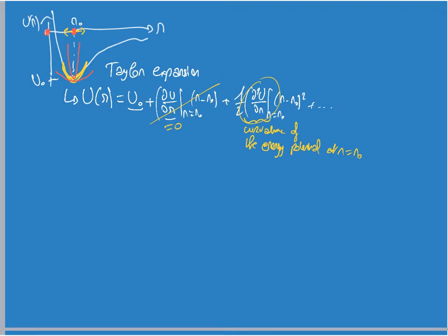So what we can do is realize that this looks very similar to the energy of a spring. If you have 2 points that are separated away from each other and attached with a given spring with a spring constant K, then the energy is given by 1/2 times the spring constant K times the elongation squared, the elongation being the distance L between the 2 points minus the equilibrium distance L naught, when the spring is at equilibrium with no force being applied to the spring. So this expression here that we get for the energy between the two atoms looks very similar to the energy that you get for a spring.